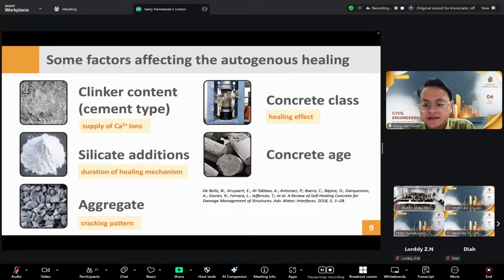And lastly, it's about the concrete age. Concrete age is also very important with respect to the healing mechanism. Because concrete at a young age, let's say 7 days or 14 days, also contains unhydrated cement in the binder system, and later they will develop new tobermorite gel or calcium silicate hydrate gel as a result of the ongoing hydration. But with old concrete, most of the cement particles have been hydrated, so they also need some calcium from another source in order to let the autogenous healing work. So these 5 factors are the main factors affecting the autogenous healing mechanism in traditional concrete.